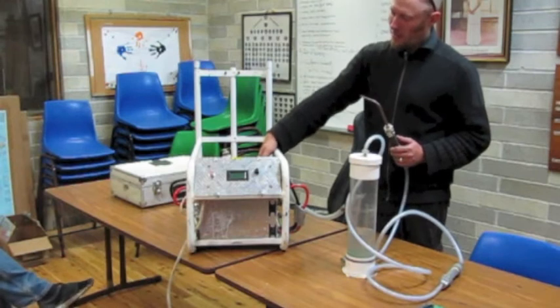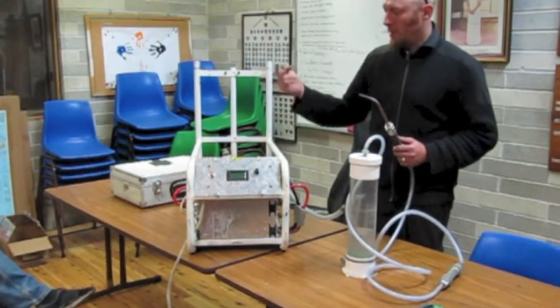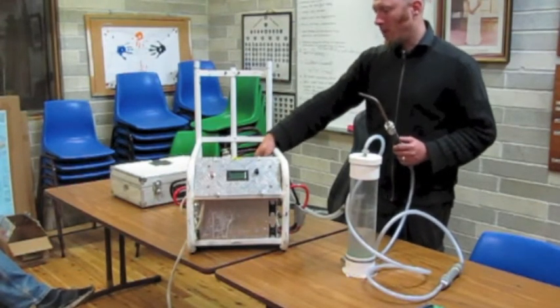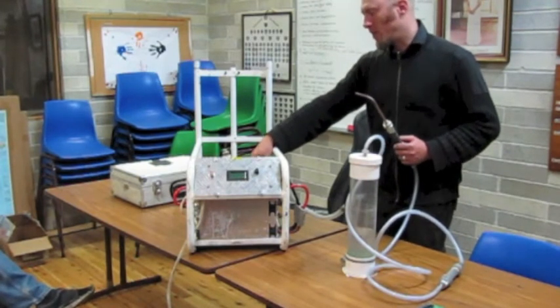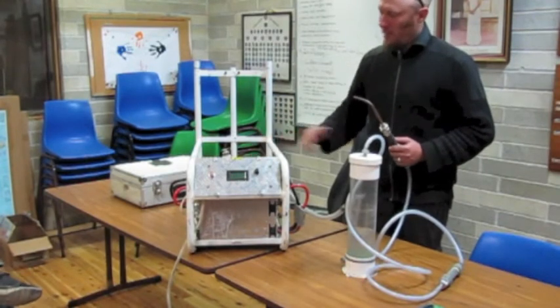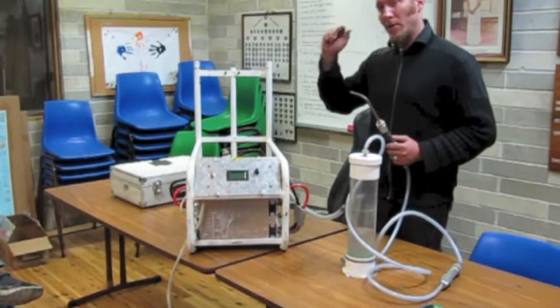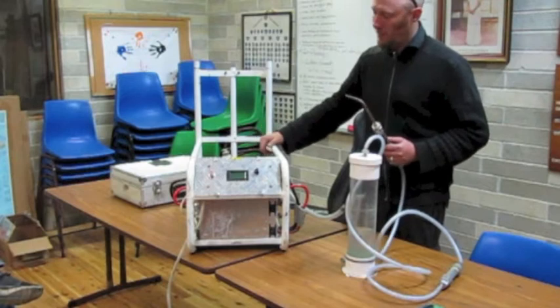In there it's an alkaline mix, so it reverses. But the plates will not last forever, because they will corrode after a point, because they are marine grade stainless steel 316. After a point they will go. The best is to use nickel or titanium.